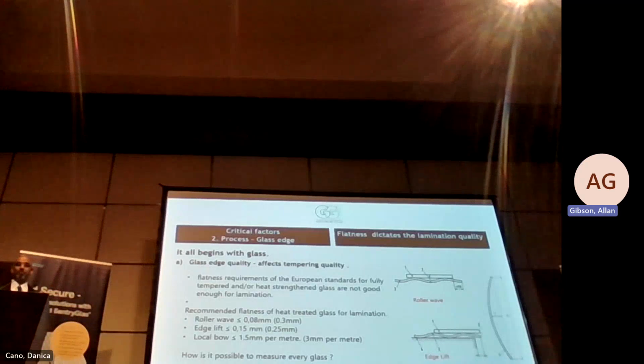What is the recommended flatness for laminated, heat treated flat glass? It is something like this. Roller wave should be less than or equal to 0.08 mm, compared to the 0.3 mm which is the standard. Edge lift, 0.15 mm compared to what you have in the standard, which is 0.25. Local bow, 50% down, less than 1.5 mm per meter compared to 3 mm. So the question is, I have 10,000, 20,000 square meters of glass laminated. How do you control it?